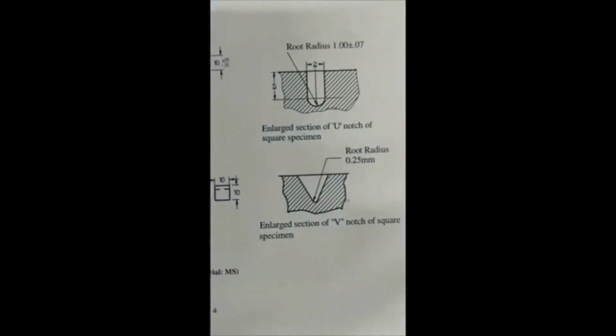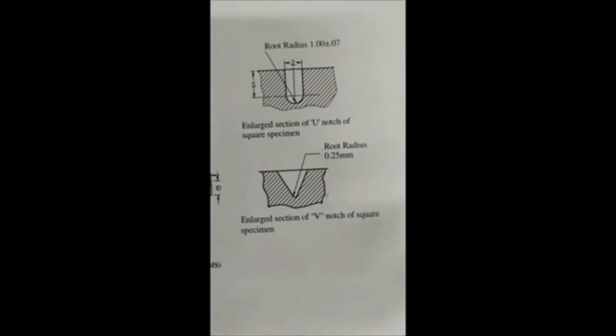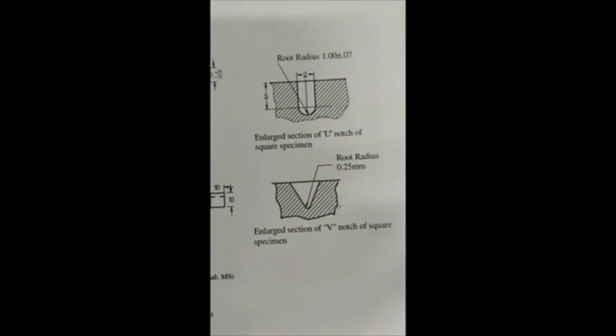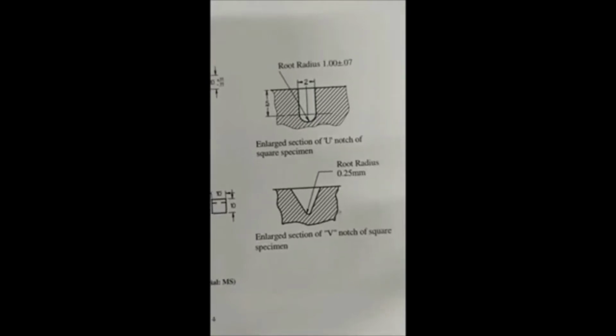You can see clearly it is mentioned. This is the notch. This is for Izod, this is the specimen, and these are the specimen dimension details and notch geometry. The angle is 45 degree. Root radius for Izod is 0.25, and for Charpy 1 plus or minus 0.07 mm. Everything will be given as a soft copy as well as in the video. We will provide you this manual copy so that you can easily understand.